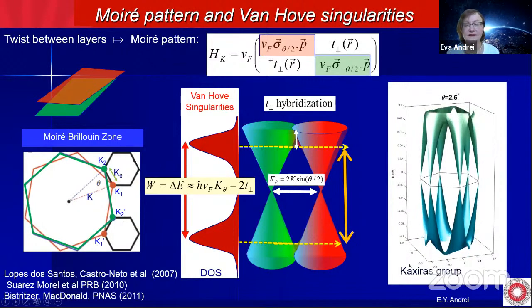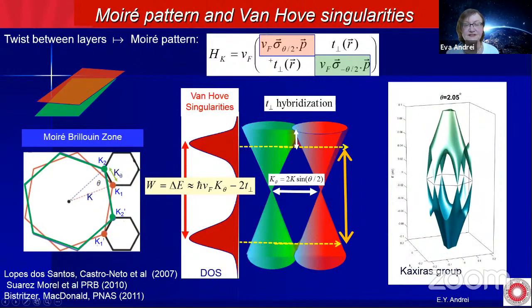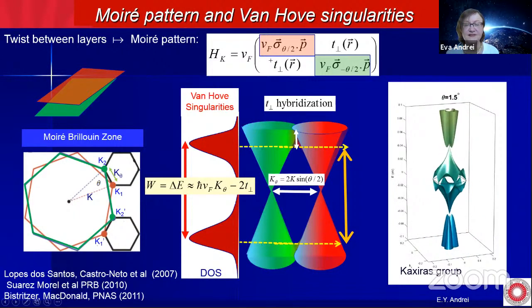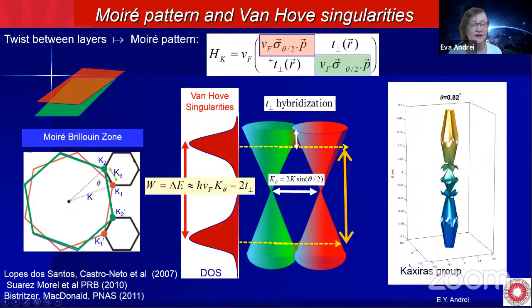Okay, so this is a simulation of the band structure as a function of twist angle. You see, as the twist angle decreases, you break the band structure into smaller pieces, and when you get to the magic angle 1.1, you have a flat band. So this is exactly what we are seeing here. And as you keep decreasing the twist angle, the band becomes broader again.